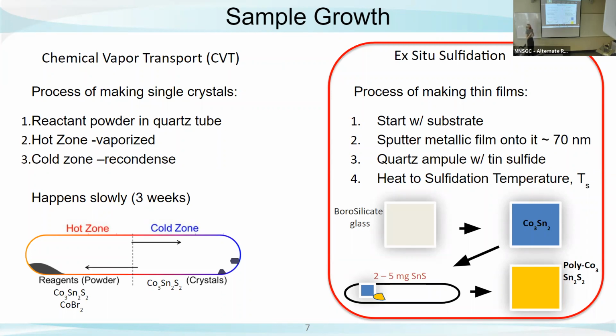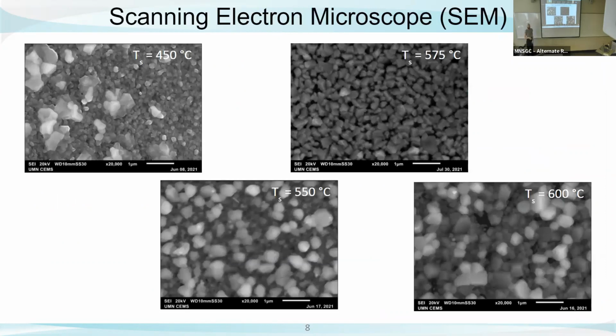And so we did this with multiple temperatures, and we wanted to see what our samples looked like, because a big thing with films is that we want our films to be homogeneous and super smooth. So if you take a look at my images, they're all in 1 micron. And as our sulfidation temperature starts at 450, we can see that there are big, large chunks that are just chilling outside or on top of all of these like mini grains. And so as we heated the sample, we saw that the grains started to get a little bit more uniform and smooth over the entire surface.